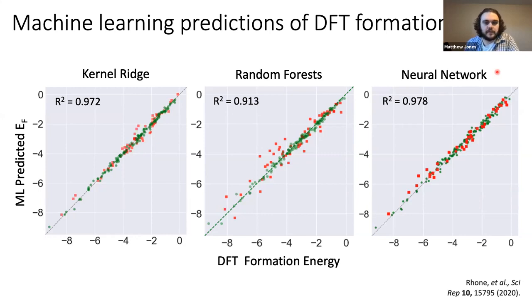How much training data goes into some of these models? So in the end, I told you that I used about 200 to begin with. It turned out at 200, I can get pretty good formation energy predictions, but the magnetic moment predictions were pretty poor. So for this, I had to increase my data set to about 300. And at around 200 or so, if you plotted the model performance versus data set size, you find that the performance starts to plateau for this data set and for these descriptors. And then you can kind of stop at around 200 for this data set. When you say 200, you mean 200 samples? 200 samples, yeah. Gotcha. Okay. Cool.